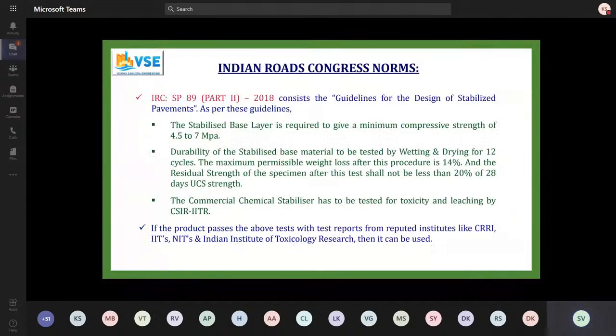So typically we are following IRC SP 89 Part 2 2018, which shows the guidelines for design of stabilized pavement. There are about 3 main factors in SP 89. One is that the stabilized base layer should have a minimum compressive strength of 4.5 to 7 MPa. The second is that the durability of stabilized base should be tested by wetting and drying for 12 cycles.